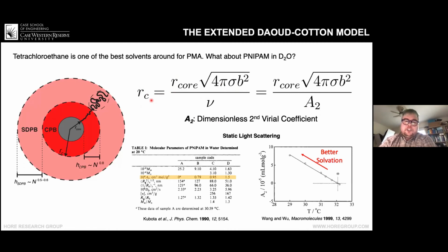So we can go into the literature, and we can go back to 1990, and actually the second virial coefficient has been measured, and we just have to renormalize this to get the dimensionless version. But you can observe that there's quite a bit of variation here. This value of 0 is taken at the theta temperature, which is 30.5 degrees. These values are taken at 20 degrees C, and you see that they vary from each other. And the only thing that's changing here is the molecular weight of the polymer. So there's a molecular weight effect that's showing up in the virial coefficient.